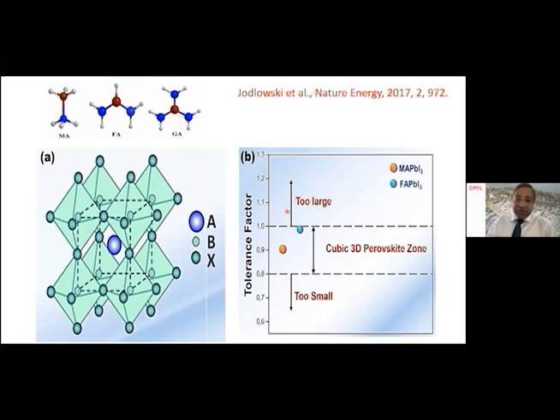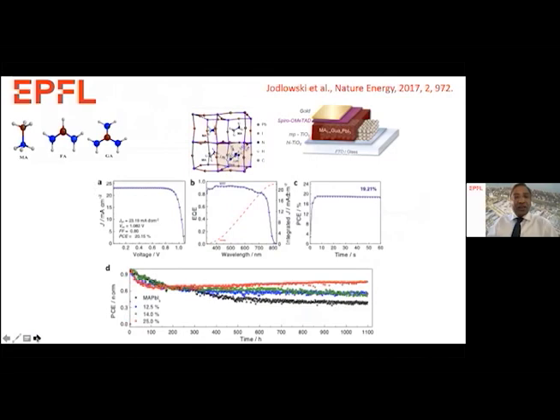So guanidinium comes in here, too large. But if we combine these larger cations with the smaller cations, we can accommodate the larger cation into the smaller cations. Therefore, we can increase the stability of this perovskite composition. It's shown here, this is a theoretical analysis. The guanidinium has three NH2 groups as shown here. These three NH2 groups interact with the iodides strongly, so enhancing the hydrogen bonding is one of the characteristic features of these perovskite materials. And that significantly enhances the stability of this material when we have 25% guanidinium and 75% methylammonium. The configuration is shown on the top right side.